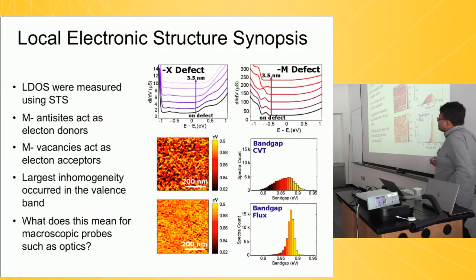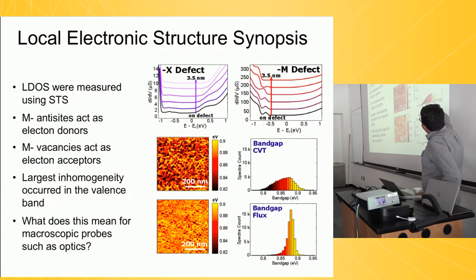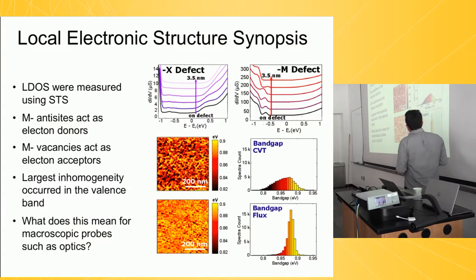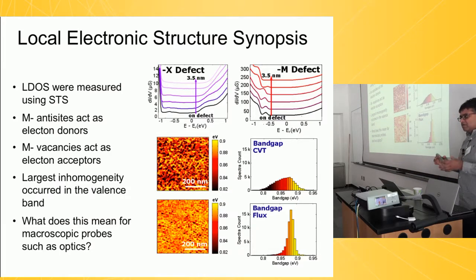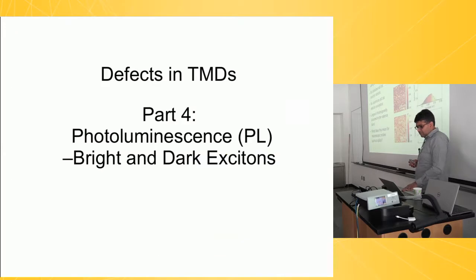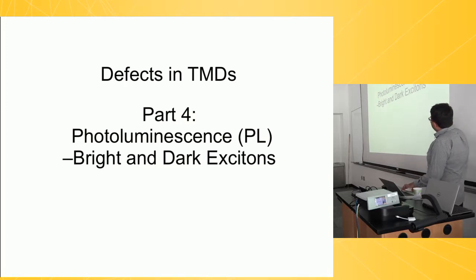Okay, good. So here's a summary of this part. We see that each of these defects produce donor states and acceptor states respectively. And if you look microscopically at the gap that this material presents for an optical experiment, it's incredibly disordered. So the question then to ask is, do you see any signature of this when you do a simple optical measurement? And we did one of the simplest measurements you can do, which is to measure light emission from these